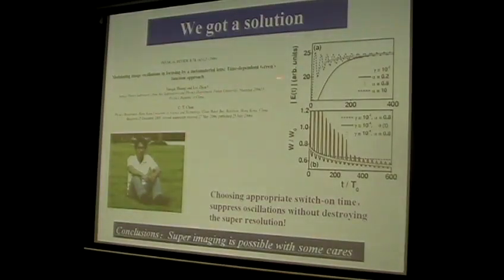In this paper, we found that we can have another freedom to suppress this oscillation. Because we know that this oscillation is caused by the beating effect with another surface wave property. If we can choose an appropriate switch on time to avoid exciting this surface wave, we can suppress this oscillation without destroying the super resolution at all.